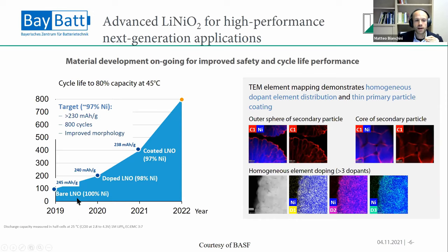And so if you take a bare lithium nickel oxide, this can easily have 245 milliamp hours per gram. But the cycle life before it hits 80% of its initial capacity is only about 100 cycles. Then one can do doping. So one can do elemental substitution of small amounts of substitutional elements that need to be homogeneously distributed, as you can see from these TEM images here. And you can already double the cycle life.